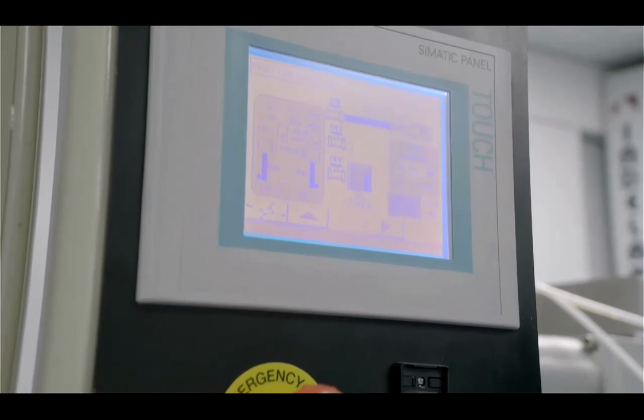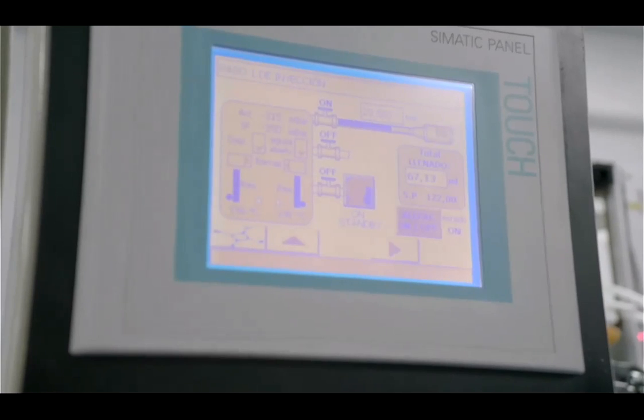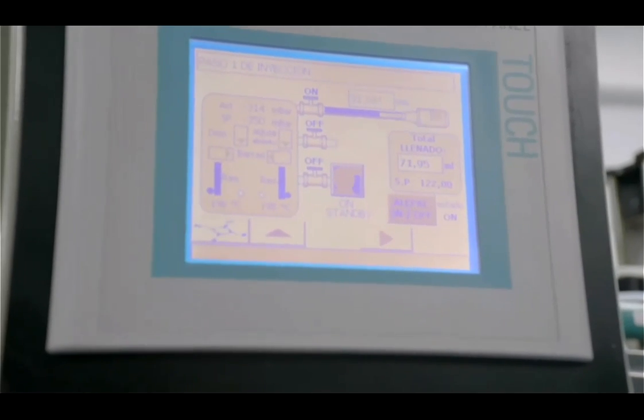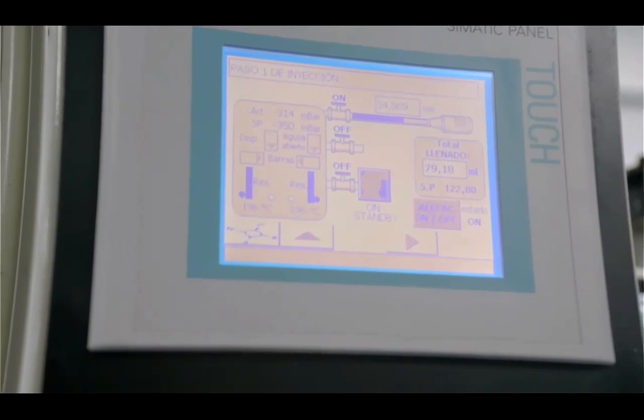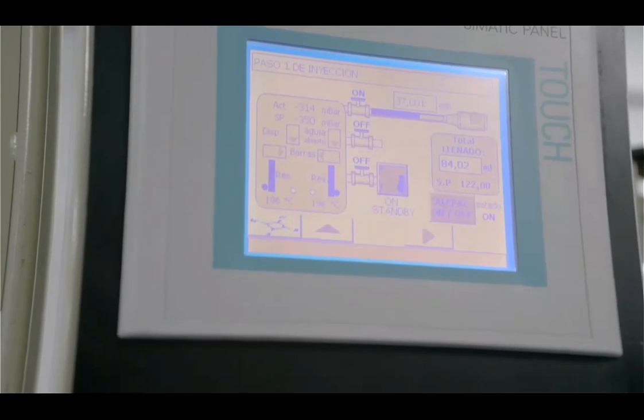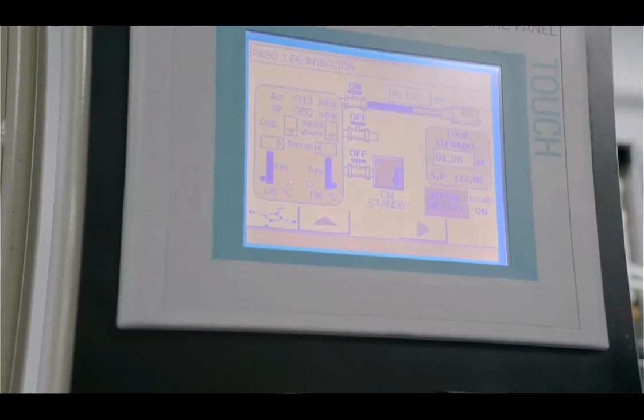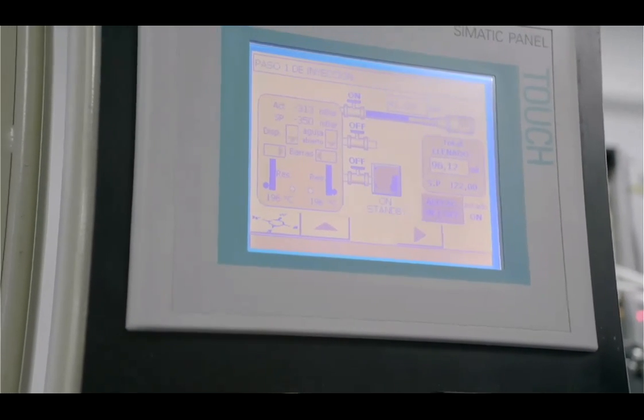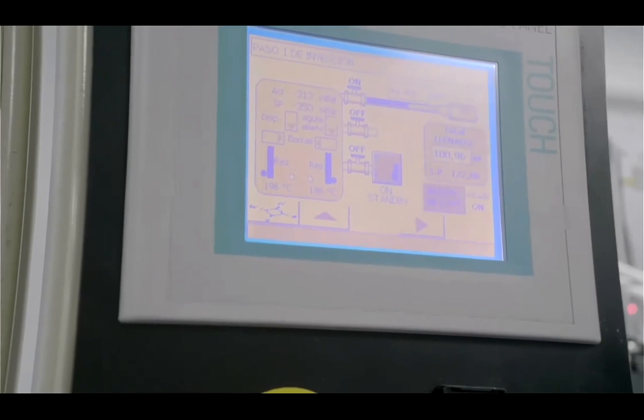This evacuation and partial filling is repeated several times, depending on the cell type. It will depend on the electrode, and it will depend also on the type of electrolyte. Okay, because sometimes some electrolytes are easier to be introduced in the pores of the cell. Finally, once we have finalized with this massage, the pouch foil will be sealed under vacuum.